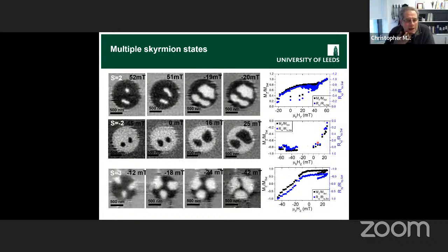Well, in the end, we had to measure quite a lot of different disks under quite a lot of different conditions to really see what was happening. So here's an example where we've got 2. I mean, this is definitely a Skyrmion. This is stretched out to be a domain, but there's 2 objects, and you can blow them up into domains. This is -2 because the contrast's the other way around. Here there are 3 objects. This one's probably touching the edge, maybe this one too. They're certainly touching the edge when you blow them up into domains, but you can still count 3 objects inside the disk.